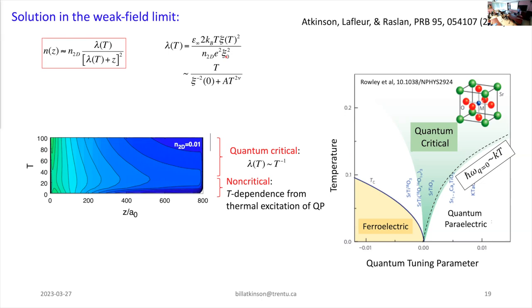Okay, you put the experimental values and it turns out it's 25 Kelvin. Correct. So there's no key explanation for why the crossover temperature is located there? It's roughly the temperature at which you start thermally exciting the phonon. You have this soft mode phonon with some frequency at the zone center that gives you an energy scale. You can turn that into a temperature scale. That's roughly what sets your 25 Kelvin. Okay, thank you.